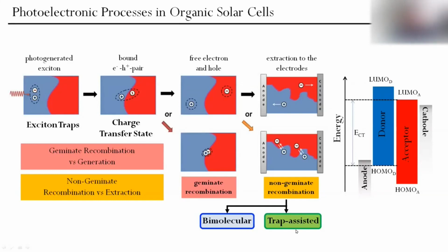And also trap-assisted recombination. So if we don't have an ideally pure semiconductor, there could be some traps, some impurities which create energy levels within the band gap, the forbidden gap between conduction and valence bands, and they facilitate recombination processes via these traps. So obviously, in order to understand and quantify all these photoelectronic processes in organic solar cells, we definitely need to investigate in detail generation and recombination processes.